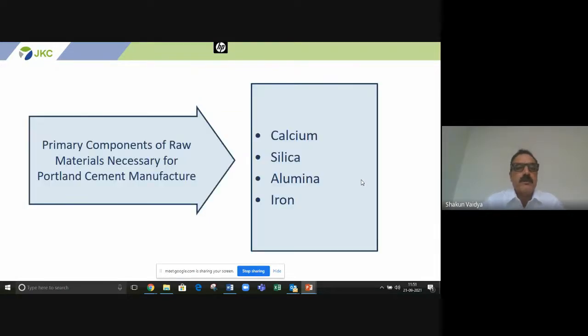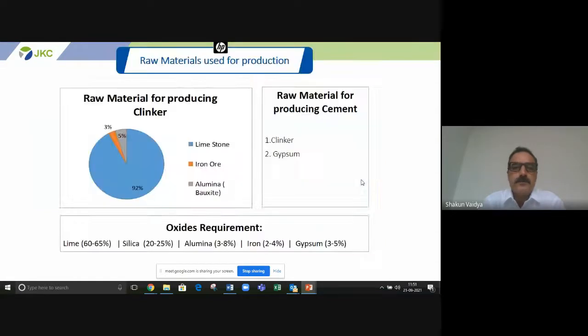So, cement, as per the constituents, the primary constituents of raw material necessary for producing Portland cement are calcium, silica, alumina, and iron. Raw materials for producing clinker are majorly limestone, and then iron, alumina, or bauxite. And raw materials for producing cement obviously are clinker mixed with gypsum. Gypsum will retard the setting time of the cement. So this is how cement is produced.